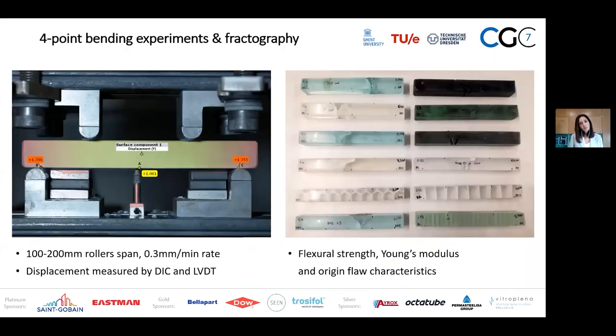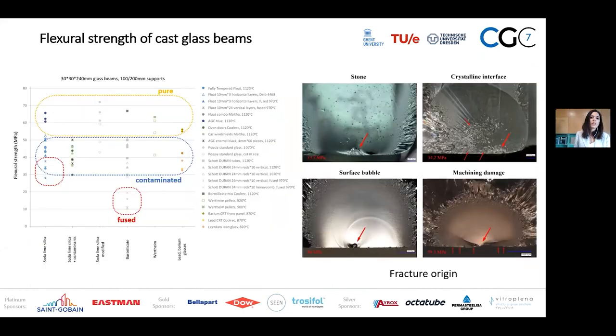And then we test our specimens in four-point bending to get a grip of their flexural strength and their stiffness, but also to understand which was this critical flaw that actually led them to failure. So if you would look at the flexural strength results, you would see that there are three main zones.